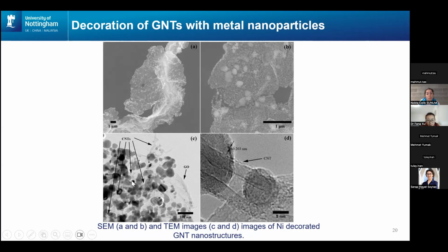From the TEM, we can observe existence of carbon nanotubes, multi-carbon nanotubes, and we can see existence of GO here as well. So the nickel particles are attached to the nanostructure. As we can see in figure D as well, existence of carbon nanotube and the nickel nanoparticles.